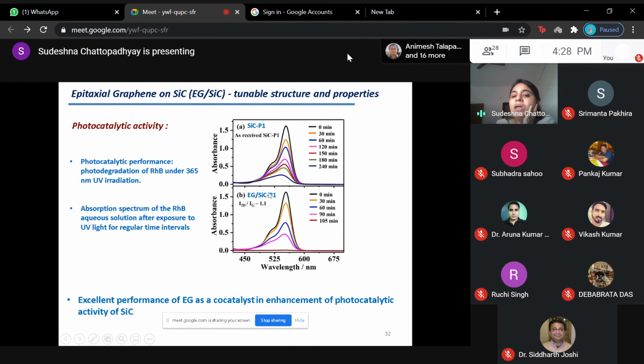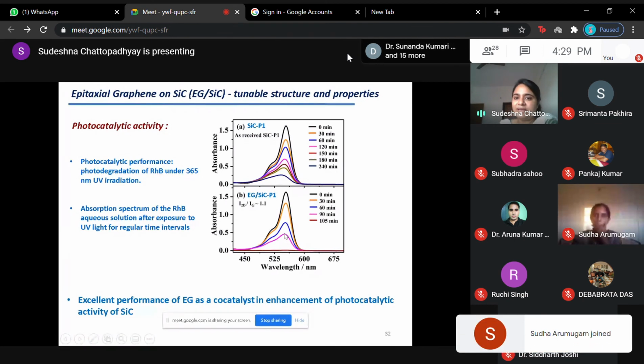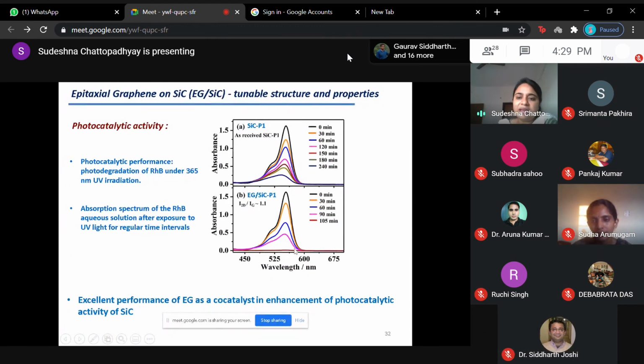But if you see when we are using graphitized silicon carbide, of course with good quality, I2D by IG is 1.1, then you can see in 105 minutes it has completely disappeared. So this maroon color line. In 90 minutes some amount was there, and after that within the next 10 minutes, 15 minutes, it just disappeared. So you can see the properties have been improved so much in presence of the graphene layers. Just a couple of layers of graphene, 2-3 layers, 1 nanometer kind of.